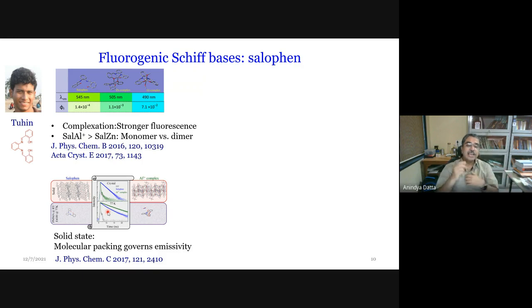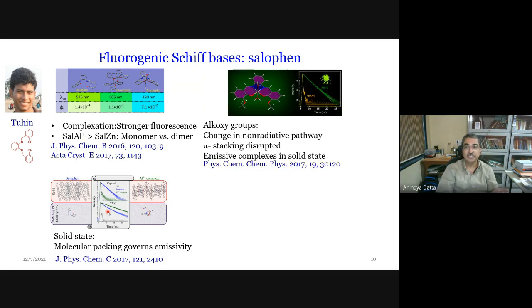So then we thought, can we introduce small functionalities like methoxy group or ethoxy group and disrupt this nice packing in case of the aluminum complex, and then do they become strongly fluorescent? The answer was yes. We introduced these methoxy and ethoxy groups. When we looked at the crystal structure, they are no longer nicely stacked, they are no longer planar, and the result is we get a strongly fluorescent solid with nanosecond lifetime.